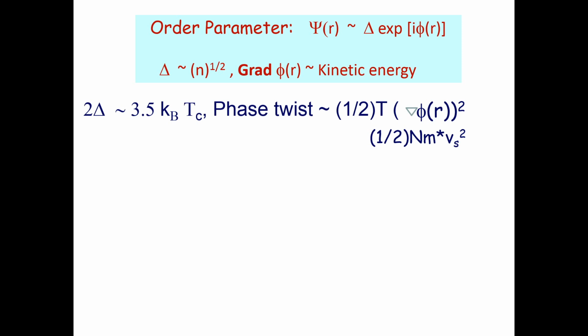You do depairing of the pairs. And the energy associated with the phase is given by this expression, half T gradient of phi squared. This is like the twisting of a spring, the energy stored in a spring. And this is equal to, in terms of the number density of Cooper pairs, the mass and the velocity squared of the superfluid. In bulk superconductors, phase is very robust. You cannot play with the phase, you can only play mostly with the order amplitude. And that's the way of destroying the superconductivity.